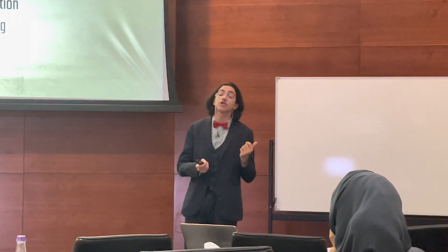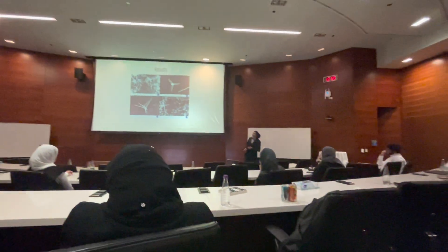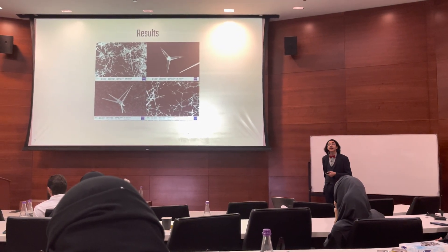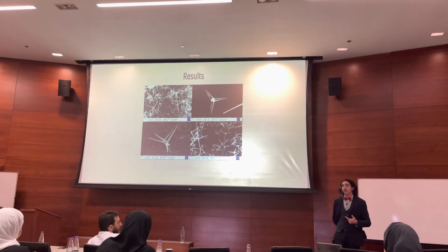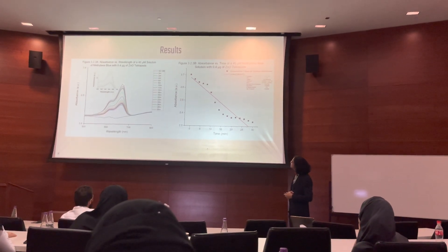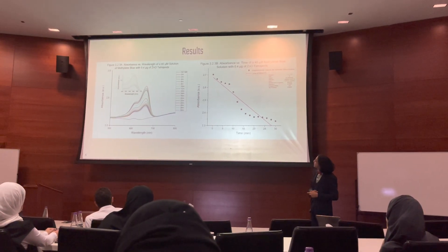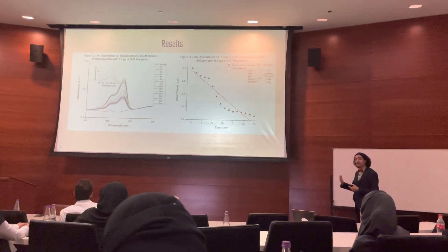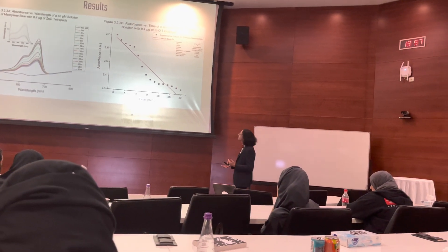I had my solution, struck it with light, and took continuous samples to study the rate of degradation. For my zinc oxide tetrapods, scanning electron microscopy confirmed they were indeed structured as tetrapods with the intended geometry. Testing degradation, you can see a peak at around 653 nanometers — the absorbance point of methylene blue. As time progresses, the absorbance decreases, which is a consequence of the methylene blue being continuously degraded by my catalyst into less detrimental organic compounds.